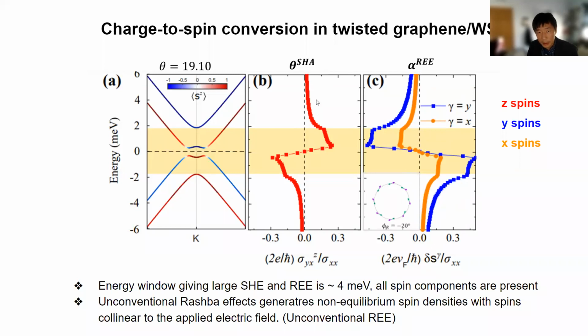What you see here is the spin Hall effect, in this case a spin current going in the transverse direction that is carrying a spin in the z direction. And here what you have is the Rashba-Edelstein effect, where you have a spin orientation along y and along x. So if you look at both the spin Hall and the Rashba-Edelstein, you basically have all spin components, the x, y, and the z.